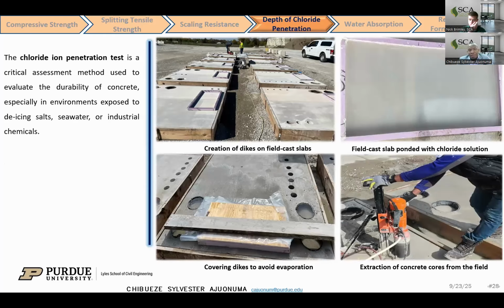Also, for the slabs in the field, they were ponded. We were able to create dikes on the slabs in the field after 28 days of casting, and then they were ponded using a 4% calcium chloride solution, and we maintained it for a period of 150 days. We tried to simulate the real world condition of chloride exposure. So the dikes were carefully covered to avoid contamination and evaporation of the solution. And at the end of 150 days, the surfaces were cleaned and cores were extracted from the diked portion, and they were split, and silver nitrate was sprayed on the surfaces to obtain distinctive profiling.